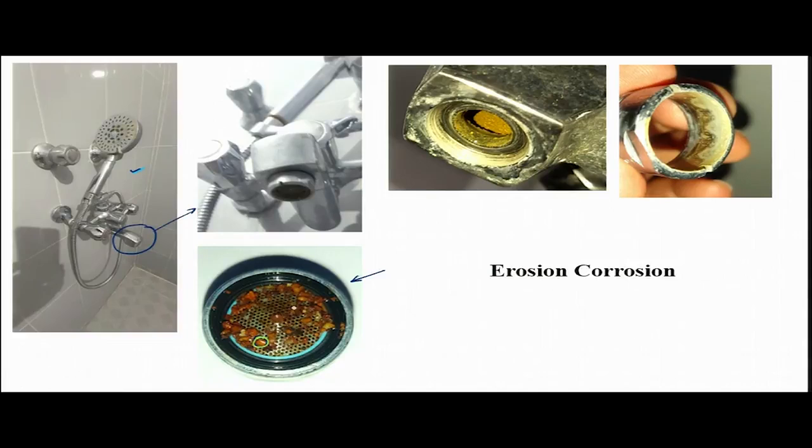Now, those sand particles are actually covered with iron rust. It's basically nothing but red rust, which is iron oxide rust, and inside is basically an iron pipe. Now, that rust is forming and covering those tiny sand particles and getting accumulated on top of that grid. Now, I opened it, and then I could see the inside part. I took a photograph after opening, this way, okay, and that photograph is given here.